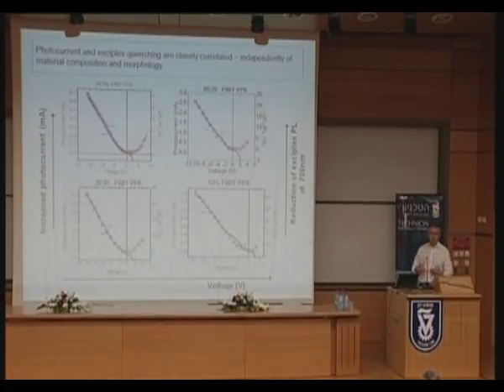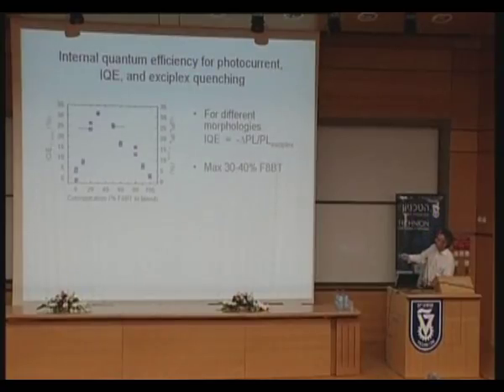Now, it turns out that irrespective of the morphology and the composition, there is a completely identical overlay of this luminescence quenching versus photocurrent in the external circuit as we go into negative bias. Very tantalizingly, if we quantify it and plot photocurrent as internal quantum efficiency, that is, the percentage of charge collected in the external circuit per photon absorbed in the film, and then use the same scale in percent for the percentage quenching of the luminescence, they just lie on top of one another. The x-axis here is the different composition of the two polymers in the blend. We have a one-to-one correspondence, the same fractional quantum efficiency for charge collection as quenching of luminescence.